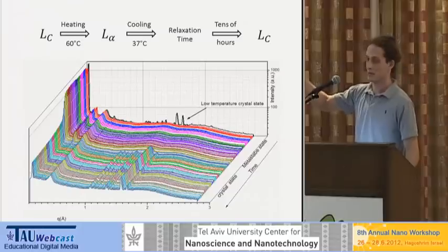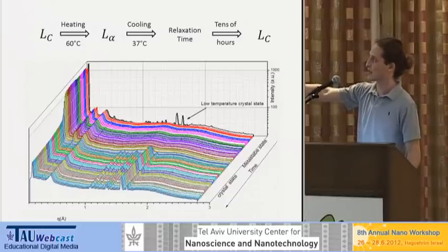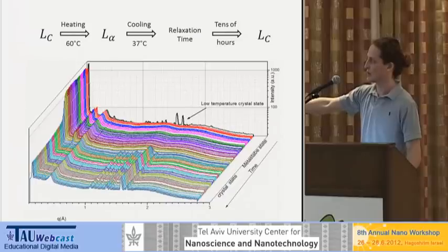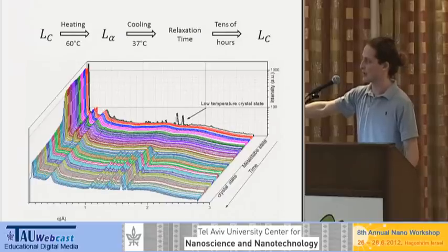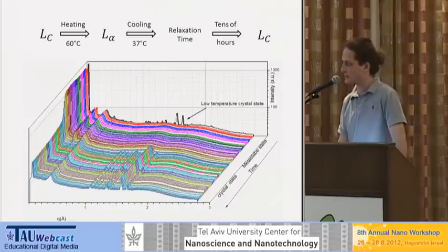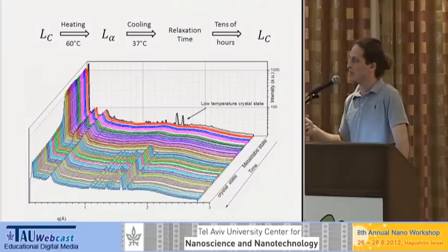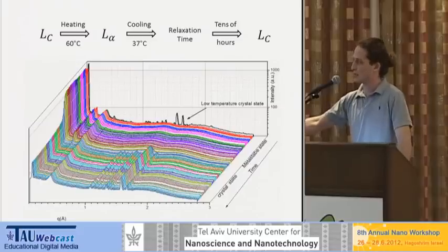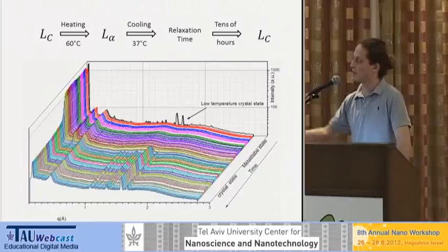Cooling back down to 37 degrees happens right over here after heating, but you see a relaxation period in which, for tens of hours, and this depends on the stoichiometry between the two lipids, there's a metastable state in which it stays in the L-alpha state, and only then does the LC reappear.